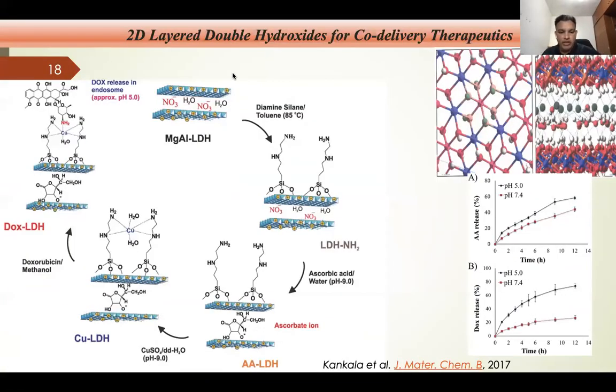And apart from MSN, in our lab we are also focusing on the generation of two-dimensional materials called LDH. In this case, this two-dimensional material is based on M2 and M3 metals, which are arranged in an octahedral way through hydroxyl groups, and it creates positively charged layers balanced with negatively charged ions. These can also be used to encapsulate drug molecules inside, and the external surface with hydroxyl groups could also be conjugated with silane chemistry, where you can use any sort of functionalization, or even load drugs on the surface as well as inside.